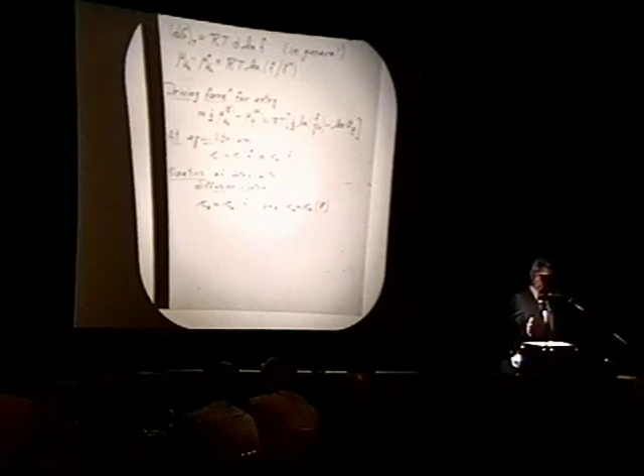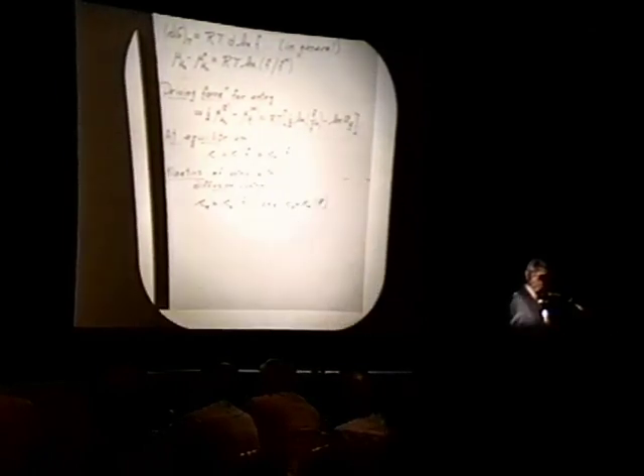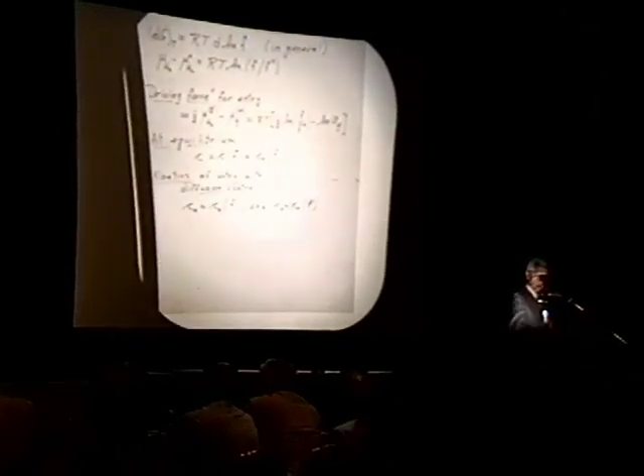Therefore, one will express the driving force for entry, not kinetics, just the driving force for entry between the gas phase and the solid solution of hydrogen in the solid, in this expression. The difference between those two chemical potentials is expressed this way. In general, this must be expressed by the fugacity expression. At equilibrium, therefore, one has that the concentration of the solid is a function of the fugacity of the gas phase.